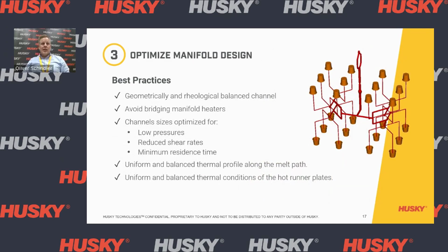What are we doing in optimizing manifold design? We ensure that all our systems are geometrically balanced and rheologically balanced, all from the melt channel inlet till the outlet to the cavity. We avoid bridging manifold heaters, to have the optimum thermal profile, to have the control between the back of a manifold and the front, for example, which is often happening that you are bridging them together to save the number of zones. Your channels should be optimized as well for low pressures, reduced shear rates, and reduced residence time.